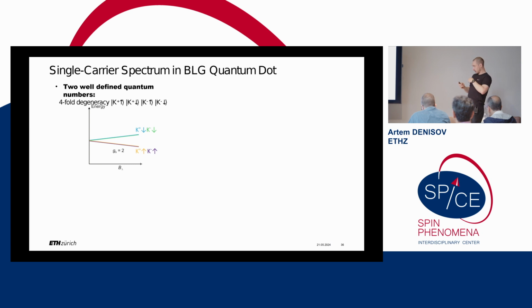Okay, so before saying how we actually managed to demonstrate it, because I'm going to talk about the spectrum of an electron or hole in a single electron dot in graphene, we need to understand the spectrum, and it takes a few steps. It's very simple, but still takes a few steps. So our wave function of the electron is a spinor. Not only do we have a spin, we also have a valley. So we have a fourfold degenerate ground state: K minus spin up, K minus spin down, K plus spin up, K plus spin down. And if we don't have any magnetic moments other than spin, as a function of perpendicular magnetic field, the states would evolve just like this. All spin downs go up, all spin ups go down, with a G factor of 2.